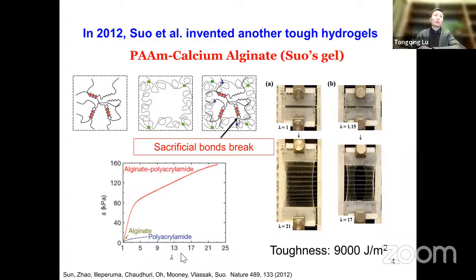We can see the stress strain curve of this double network hydrogel. Here is the PAM hydrogel, and here is the alginate one. These are two single network hydrogels. If you combine these two networks together, you can see the mechanical properties are greatly enhanced. Here we can measure the toughness of this hydrogel, which is common practice in fracture mechanics. We first stretch this material. You can see it can stretch 21 times without any pre-cut crack. If you make a crack, for example in the middle, it can still stretch to about 17 times. And we can calculate that the toughness of this hydrogel is about 9,000 joules per meter squared.